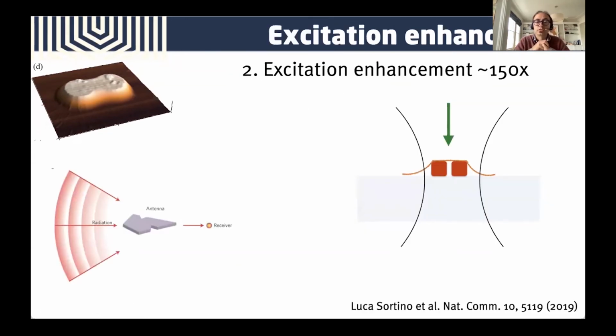Then the antennas also act as an antenna for the excitation, meaning that when we send the light into the material, the antenna will focus the light down to the emitter. So this is the so-called antenna effect that I picture here on the left. Our light beam is focused very well into the volume around the antenna where the 2D material is. And this gives us a 150 times enhancement of the efficiency in exciting the material.